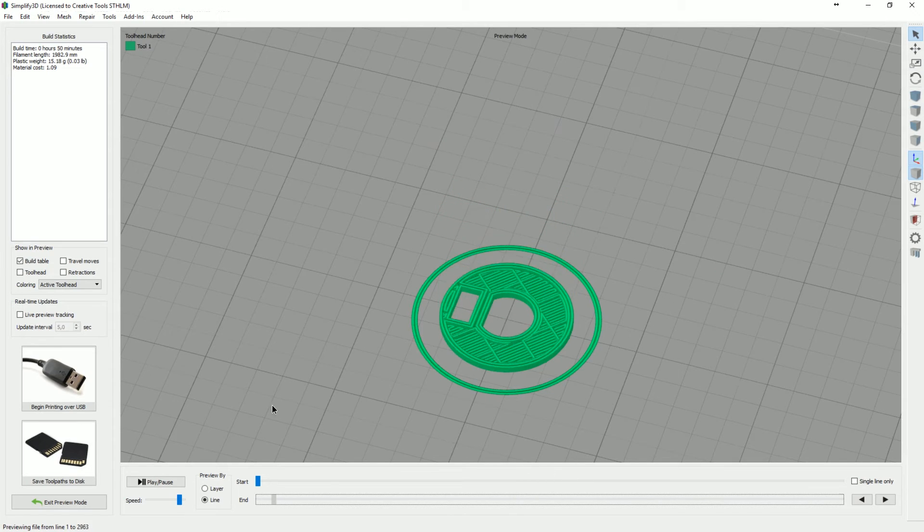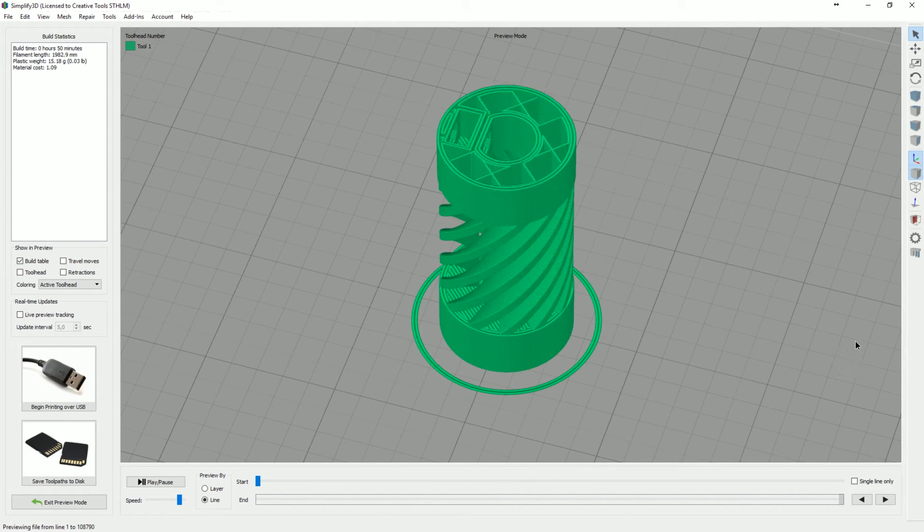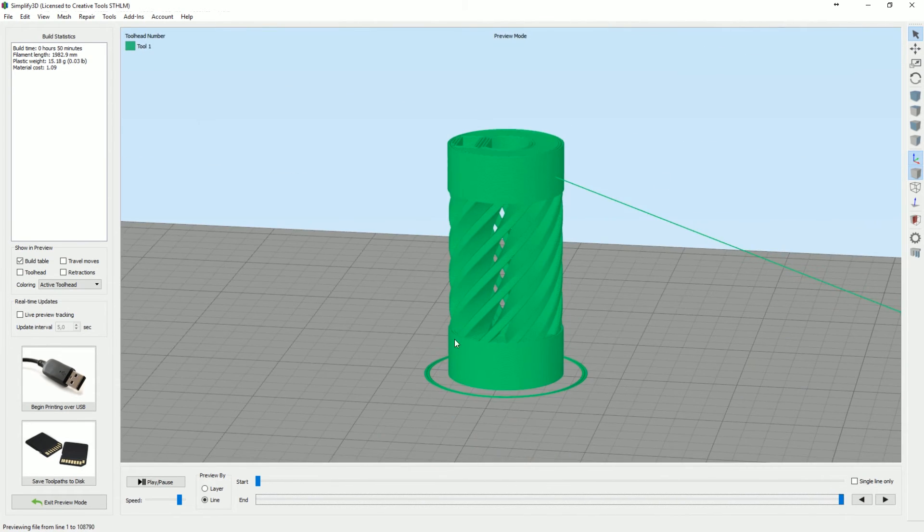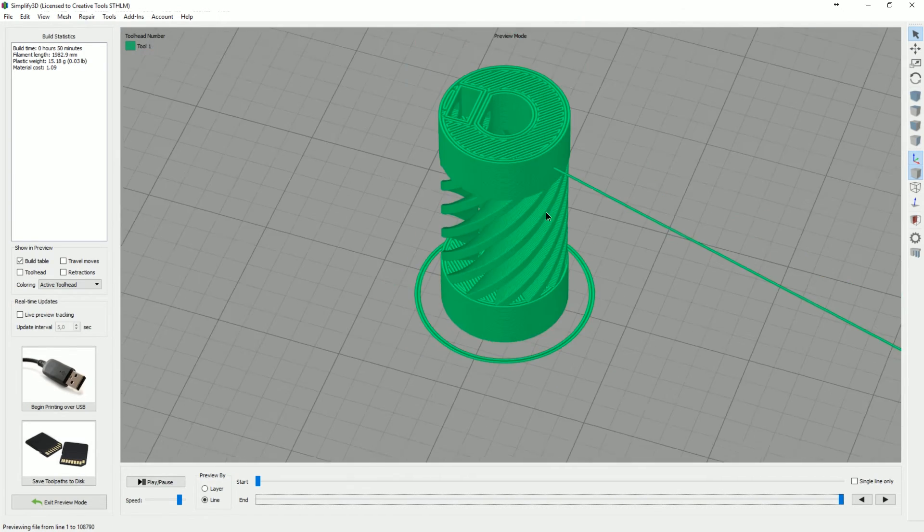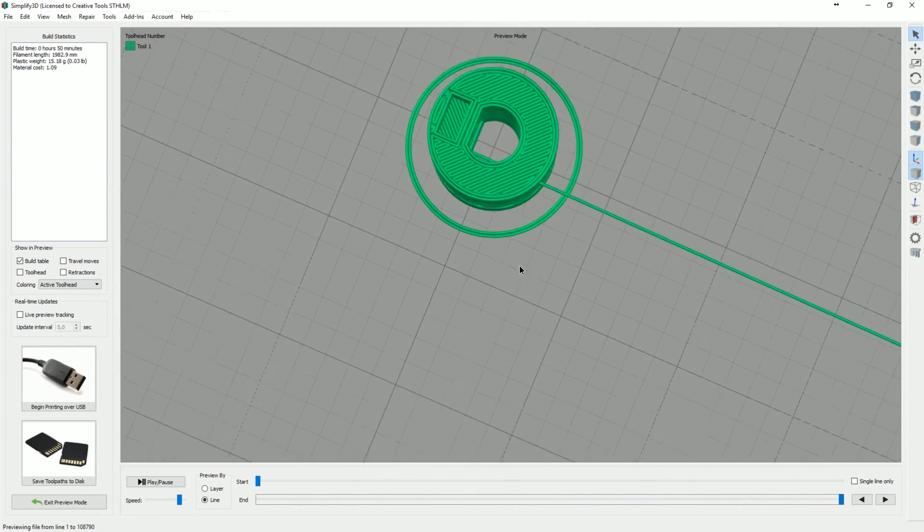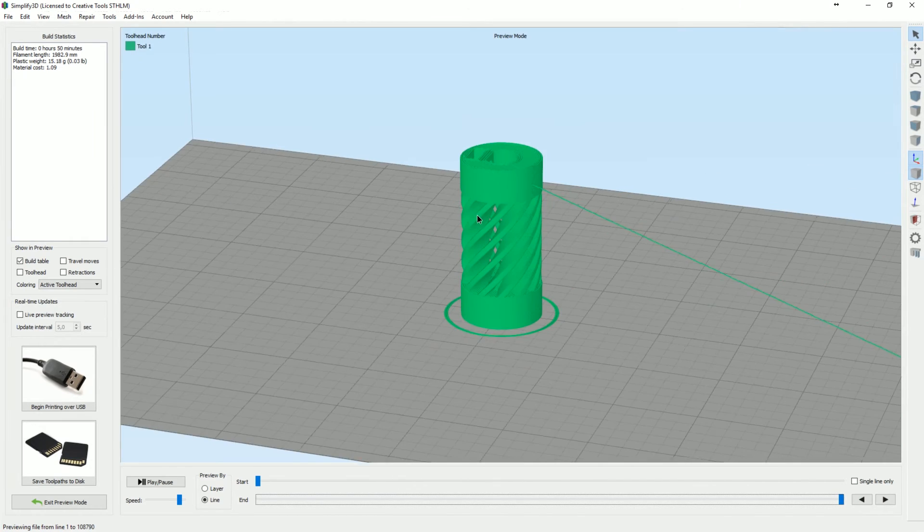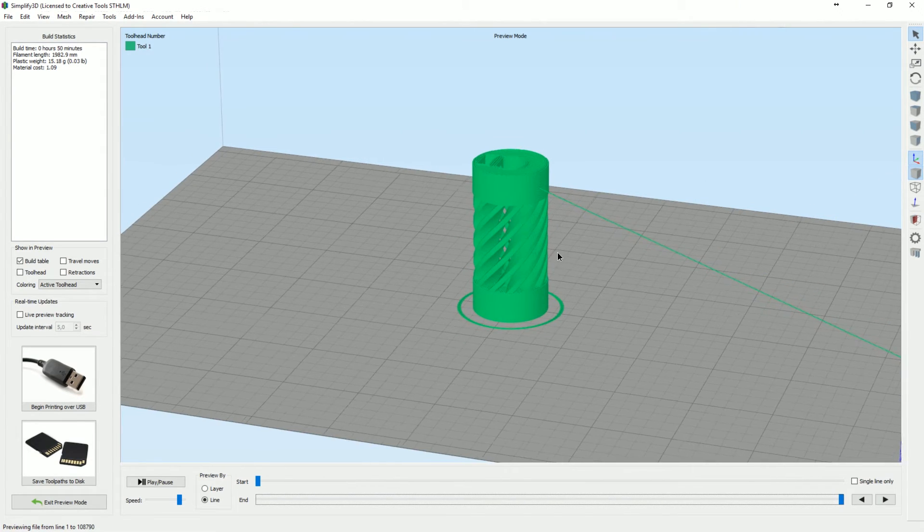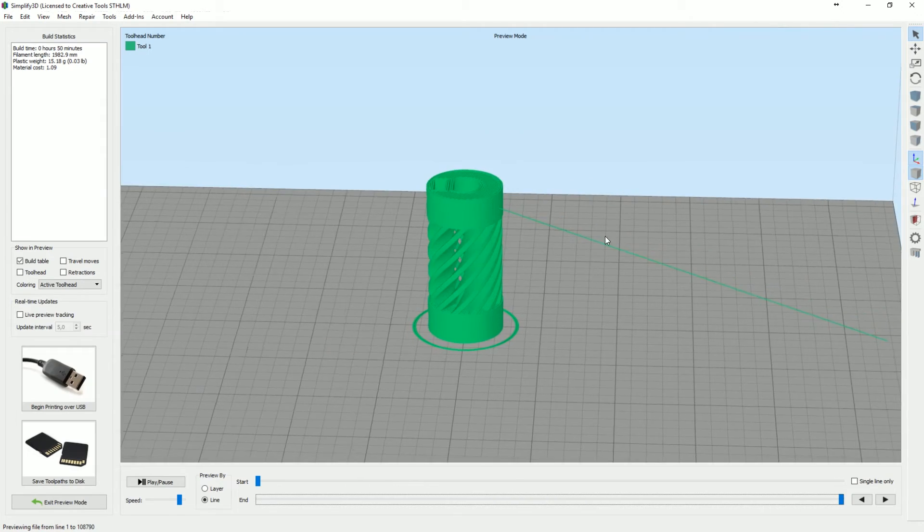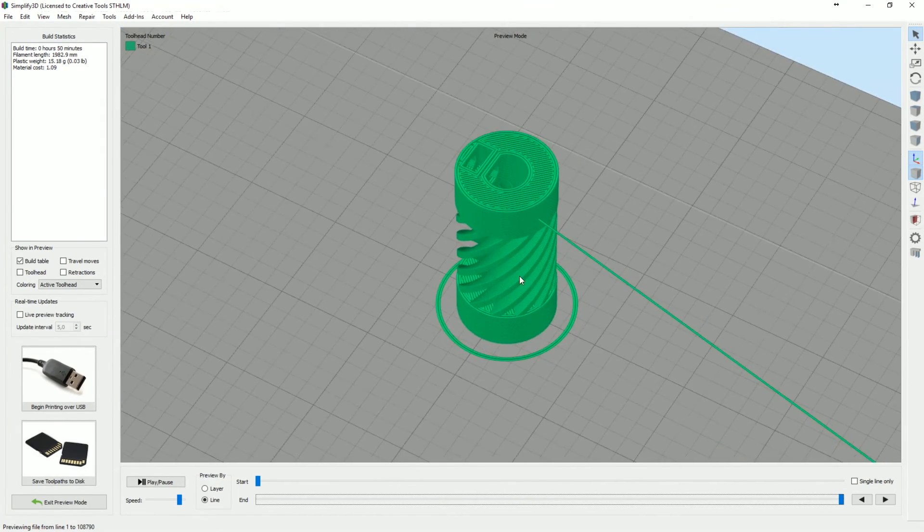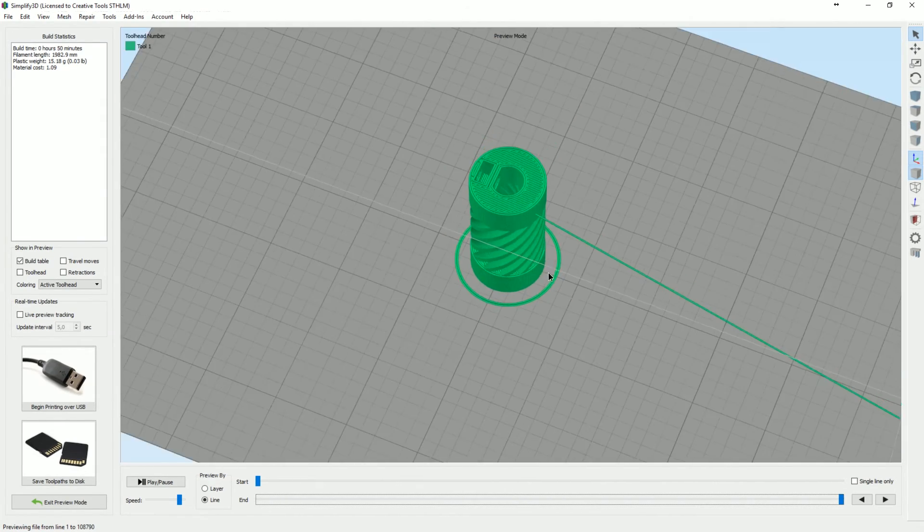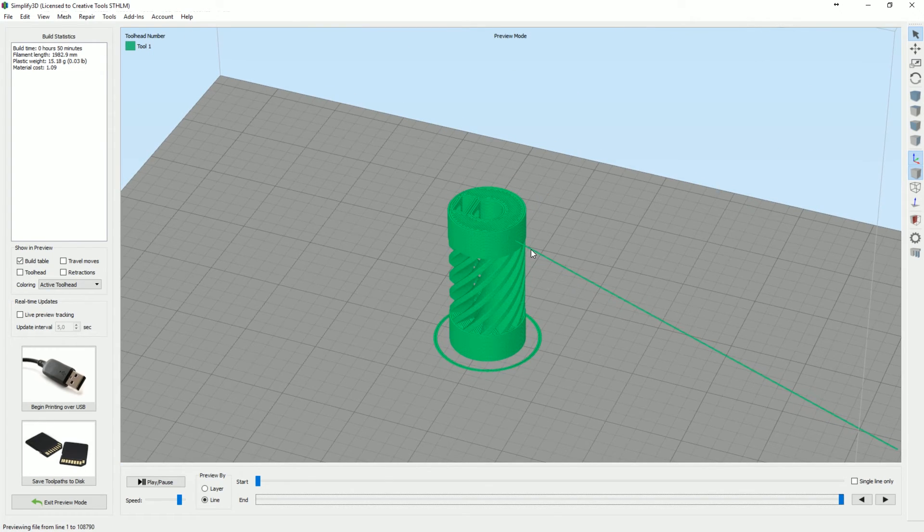I'm gonna try that out. I will increase the temperature to the recommended 225 for semi flex. In the process here, just load it as we always do. We chose right extruder only. I bumped this up to 230 in this case which I think will be good. Speed was already set low enough - I think 30 is a good starting point. Then we prepared it and we can see that this will probably be pretty neat.